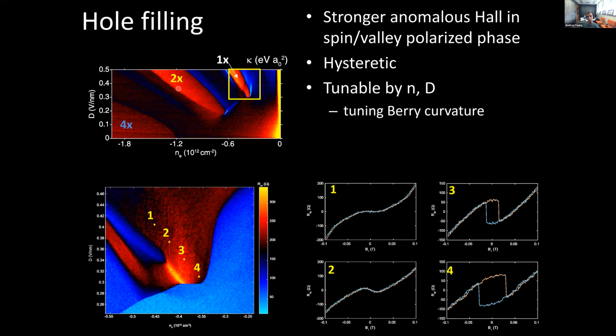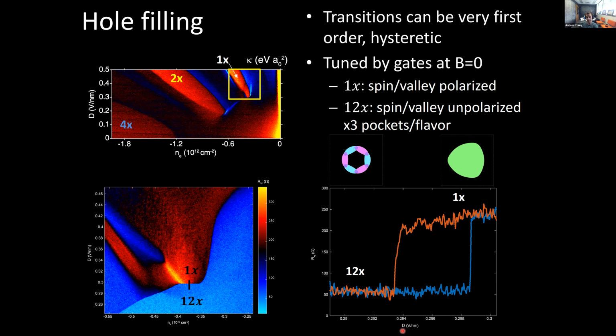So for example, within this valley polarized 1-fold phase, you see a very strong anomalous Hall effect, which can become hysteretic. And actually, if you just tune the density, or tune electric fields to cross these transitions between what we would say is a 1-fold spin and valley polarized phase and a 12-fold spin and valley unpolarized phase with 3 pockets in each flavor, you can actually see hysteretic switching of magnetic order just by an electric field, because you're just going across this phase transition.